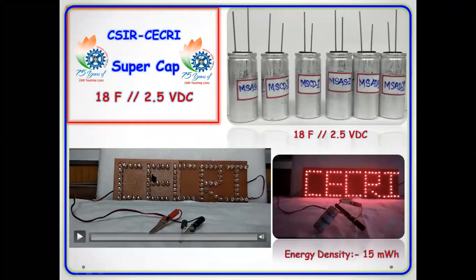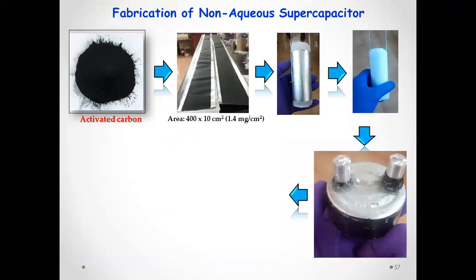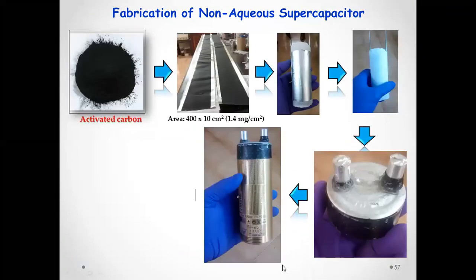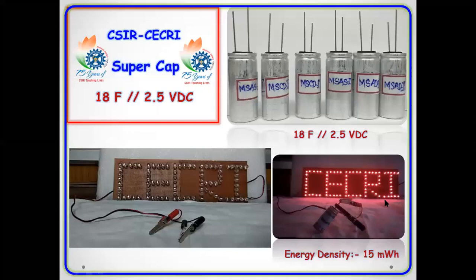I'll check whether my videos work here. So these devices have 18 farad or 9 farad, depending on whether it's one-side coated or double-side coated electrodes, which can go up to 2.5 volt. The stored energy in the system is 15 milliwatt hour. You could see the previous one is a very large one, where you could have only 30 milliwatt hour. Whereas here a very tiny device can store half of this energy.